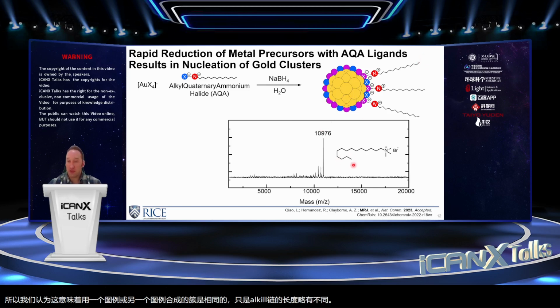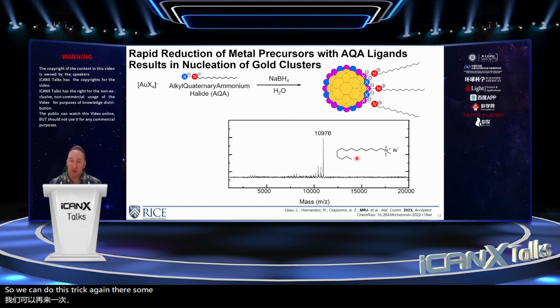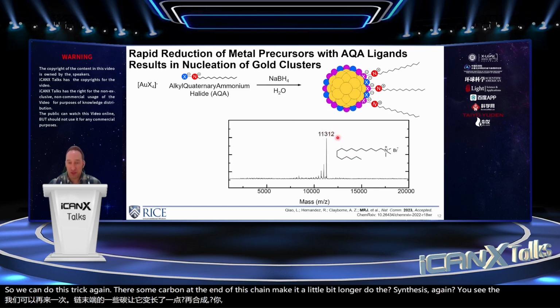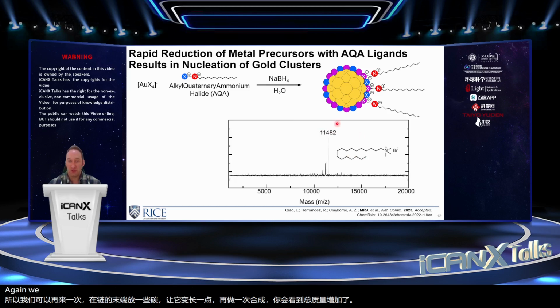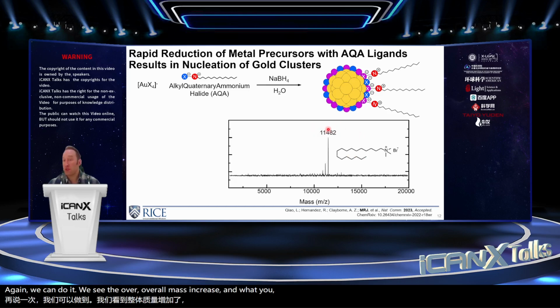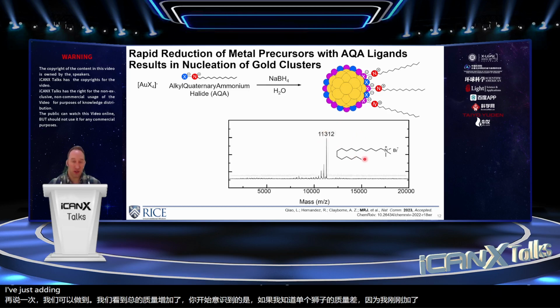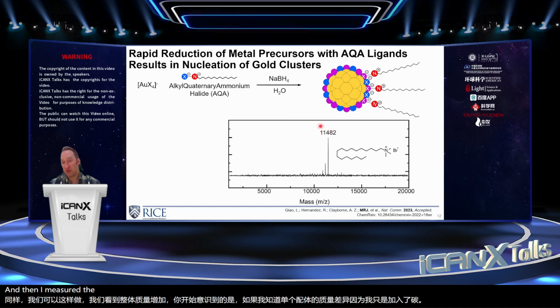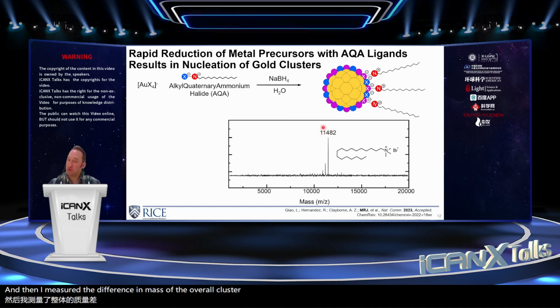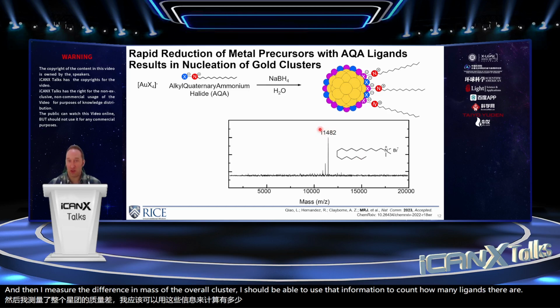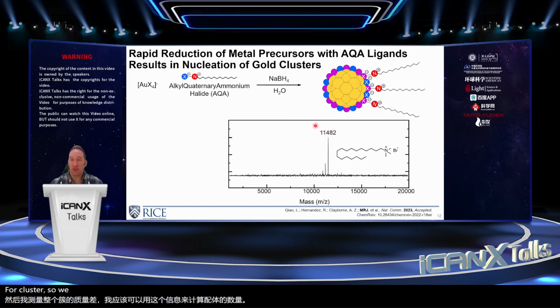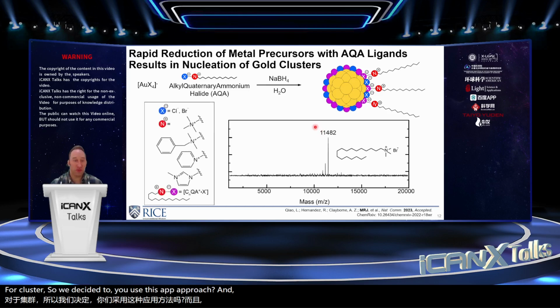So we can do this trick again: throw some carbon at the end of this chain, make it a little bit longer, do the synthesis again, and you see the overall mass increase. Again, we can do it, we see the overall mass increase, and what you begin to realize is if I know the difference in mass of the individual ligands, because I'm just adding carbon, and then I measure the difference in mass of the overall cluster, I should be able to use that information to count how many ligands there are per cluster. So we decided to use this approach, and we just threw the kitchen sink at it.